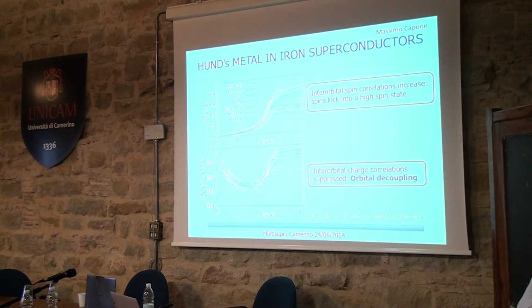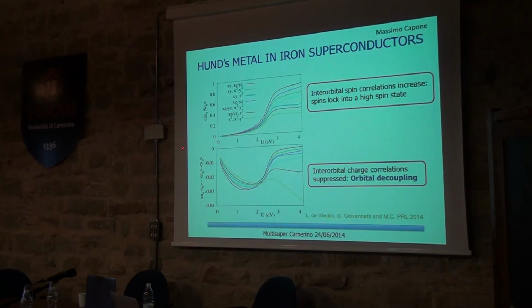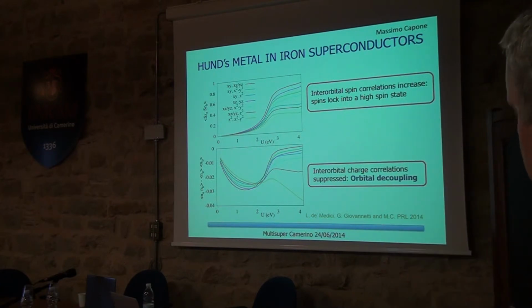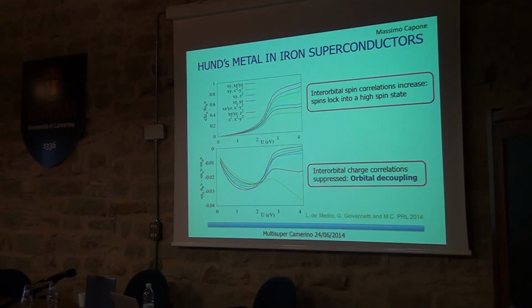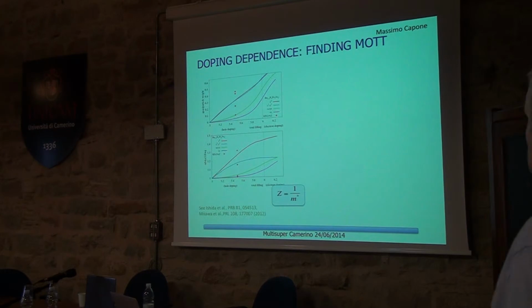Another important thing in this process, don't look at the details, these are spin-spin correlations. The spin-spin correlations increase a lot while we go in this direction because the Hund's rule is dominating. The Hund's rule wants the different orbitals to have, as much as possible, aligned spins, while at the same time the charge density fluctuations between the different orbitals are frozen. Okay? So now let's go back to the main results.